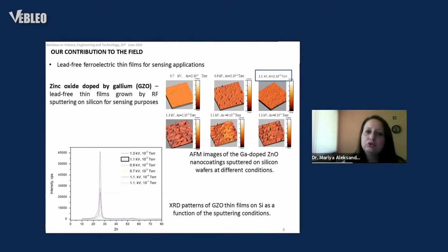Different coatings were produced by conventional vacuum sputtering in a radio frequency electrical field process on silicon substrates. And the experiments were conducted at different sputtering voltages and different sputtering pressures. Briefly, for those of you who are not familiar with this process, it is a vacuum chamber. Inside you mount the substrate and the target material that you want to be grown as a thin film. You fill the chamber with a specific concentration of inert gas and supply the sputtering voltage. It is causing ionization of the argon.